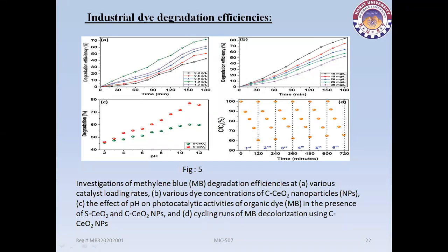The dye degradation efficiency was recorded using various catalyst concentrations. The amount of catalyst was varied from 0.3 to 1.3 gram per liter, and the results are depicted in Figure 5a. Improved efficiency was recorded by increasing catalyst concentration. The maximum degradation rate of 72.5% was at 1.0 gram per liter. After that, reduced conversion efficiency was recorded.